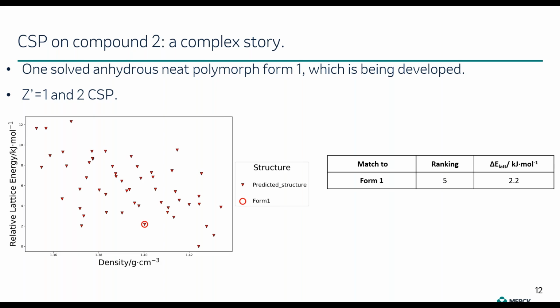Now I'm going to show you a more complex story, that of compound 2. This compound is basically a candidate drug. The lead form is an anhydrous neat form, so a single component crystal structure, and the only known form is form 1, which is the form being developed. We performed a CSP with 1 and 2 molecules in the asymmetric unit cell, and what we found out was that a match to form 1 was not the global minimum in this case, but it was ranked 5th in lattice energy, approximately 2 kilojoules per mole above the global minimum.